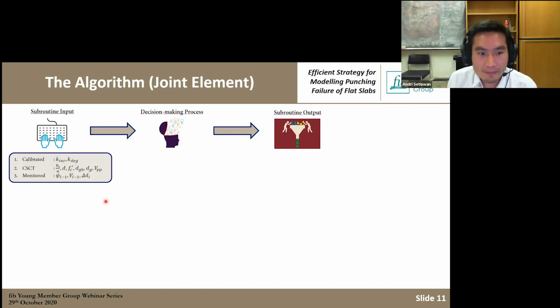So for the subroutine input, there are three different inputs: the calibrated parameters, the critical shear crack theory parameters that are used to produce the criterion, and also the most important one, the monitored parameters, which here are the rotation at the previous step and the shear at the previous step. By comparing these two, we can see whether failure has happened or not, and also the displacement, so that we can calculate the stiffness on each step. So we are going to start.